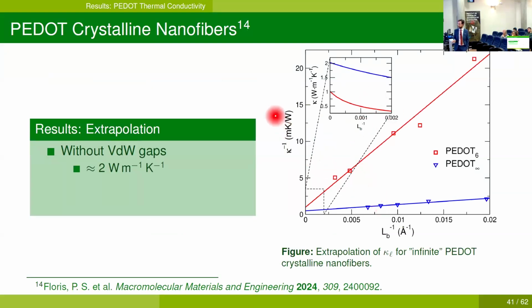So what you see in this graph is the inverse of the thermal conductivity as a function of the inverse of the backbone length of the nanofibers. What we can do with the blue dots here is fit them in a straight line, and the intercept with the y-axis will give us the inverse of the lattice thermal conductivity as a limit case, which means for infinite PEDOT chain length. And so we calculated this, and it gives 2 watts per meter Kelvin. We do this fitting basically to single out the effect of boundary scattering. And we did similar things for PEDOT chains of 6 monomers, and it gives 1 watt per meter Kelvin.